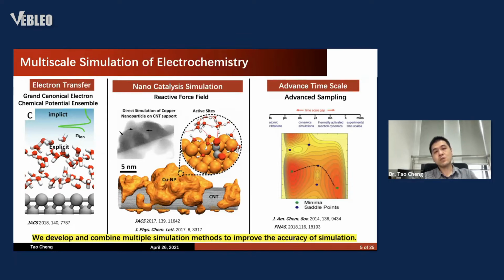This is the difference between an electrochemical reaction and a normal chemical reaction, because in electrochemistry we always have an applied voltage. The second part is that we develop models that can simulate nanoparticles. We know that for catalysis, nanoparticles usually have much better performance than the bulk. But the problem is that people don't know the structure and don't know the exact active site. So we developed methods based on reactive force fields so that we can do simulations directly at exactly the same scale as the experiment.